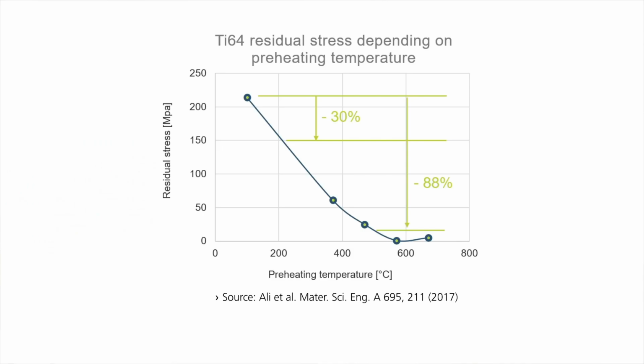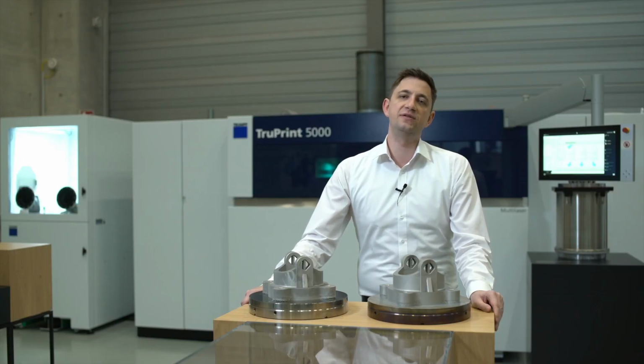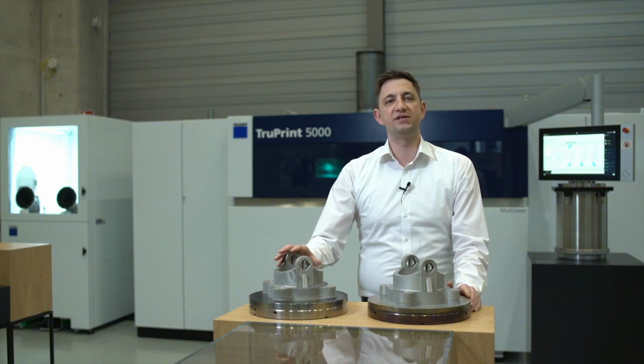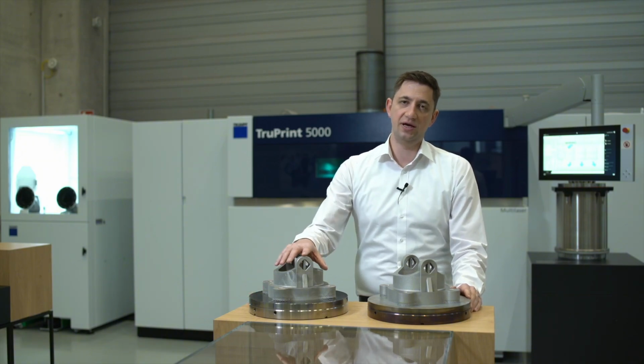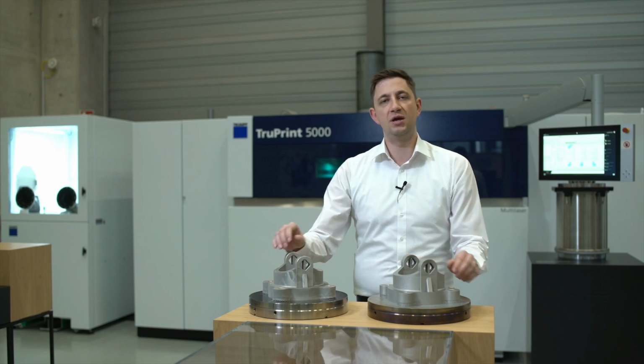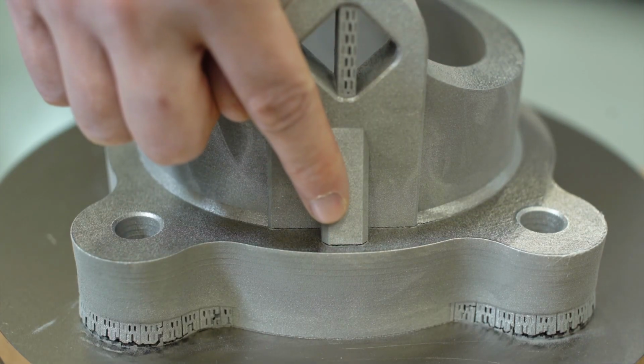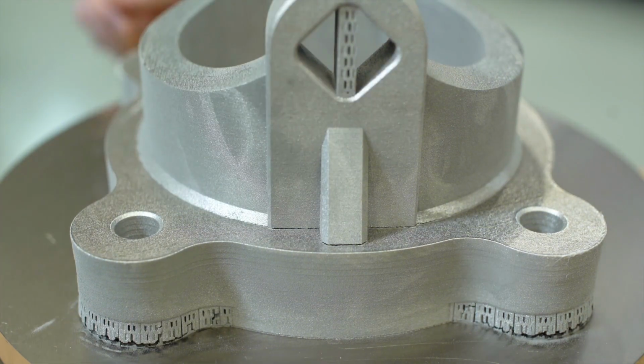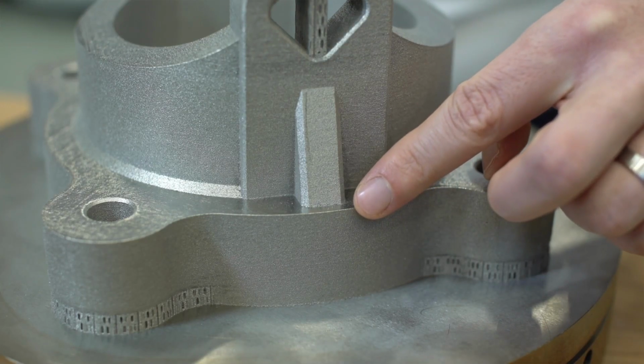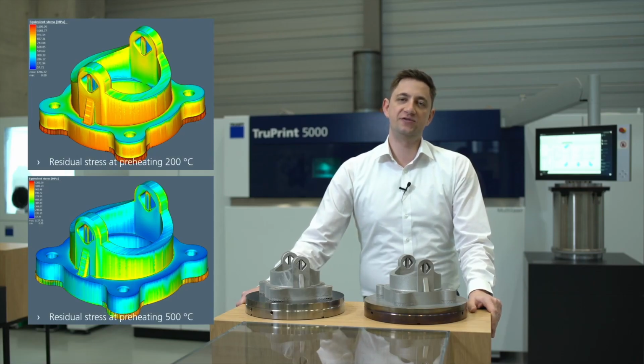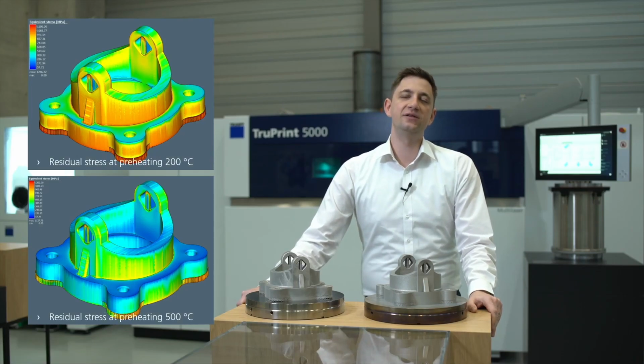Official research results with test cubes showed already how higher preheating temperatures can reduce the residual stress of titanium and with it the deviation of the part. With the TruPrint 5000 we are bringing these lab results into reality. This titanium casing shows the direct comparison of 200 degree and 500 degree of preheating. You can see clearly how one of the parts has been affected by residual stress while the other maintained its geometry. We even simulated the residual stress for both parts and you can see clearly the differences.